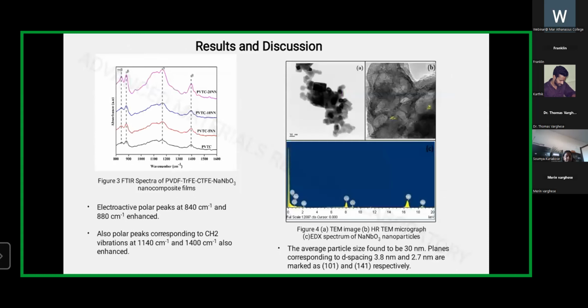And coming to the FTIR studies, the FTIR studies depict that the electroactive polar peaks of the composite films get improved. And coming to the morphological studies, we can see that the majority of the nanoparticles synthesized are spherical, and also the d-spacing corresponding to the planes 101 and 141 were also marked using the HR-TEM micrograph, and elemental composition was confirmed using the EDS spectrum of the sodium niobate nanoparticles.